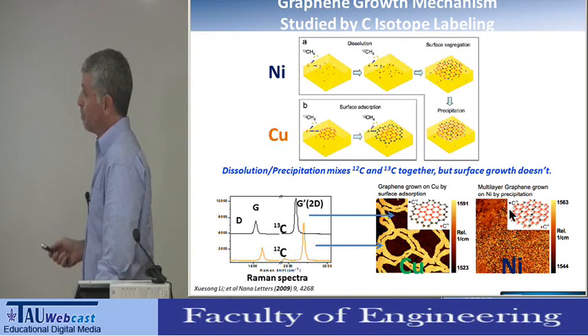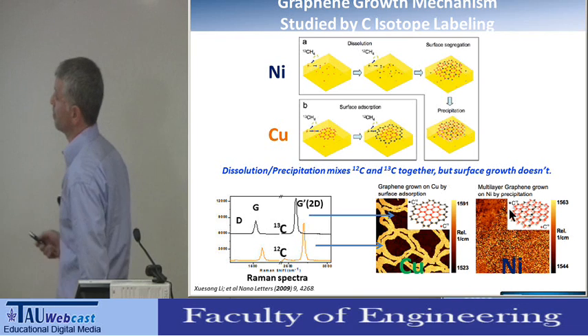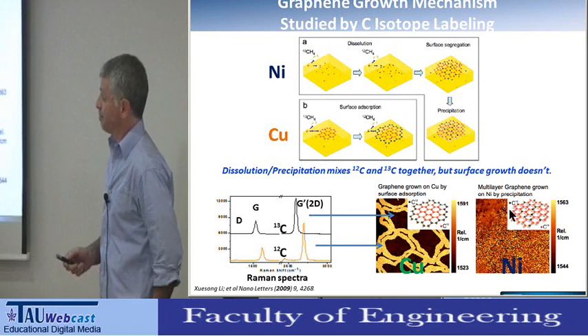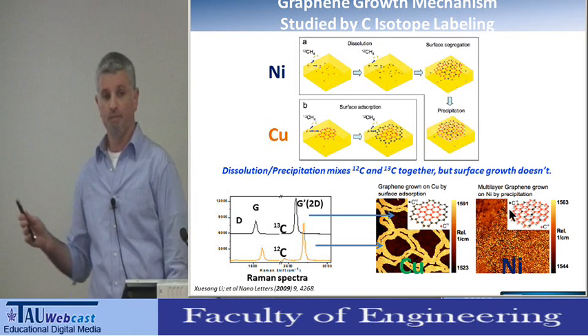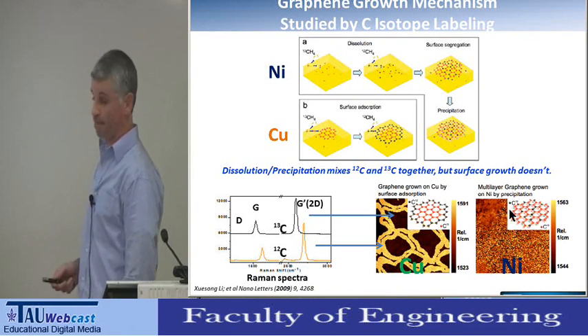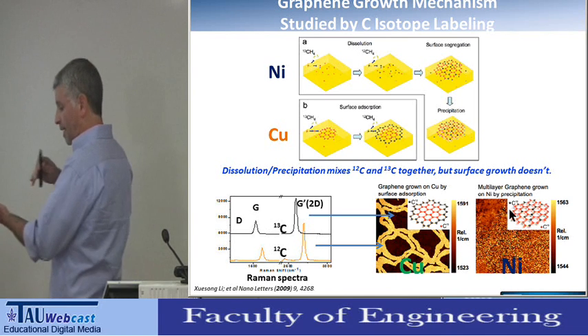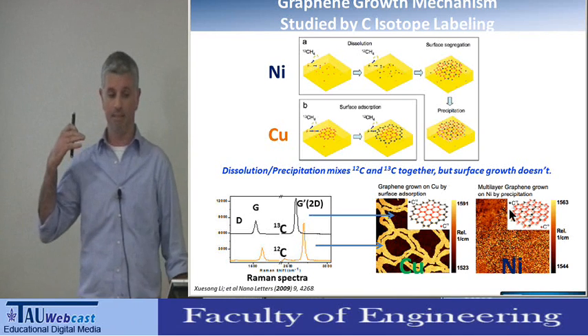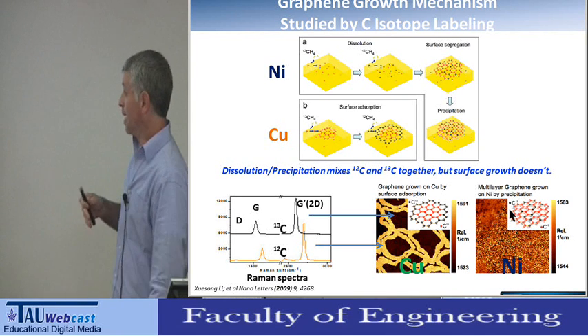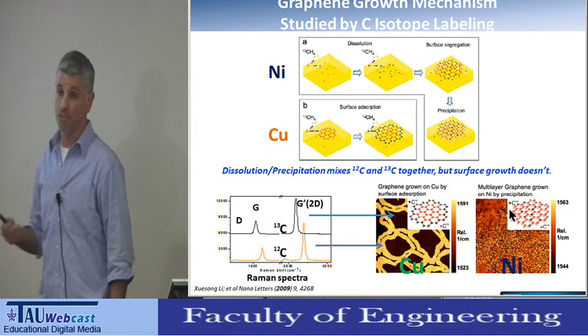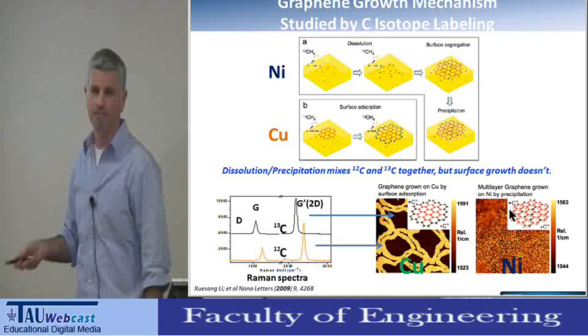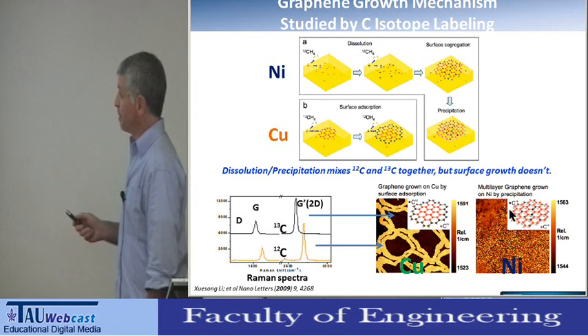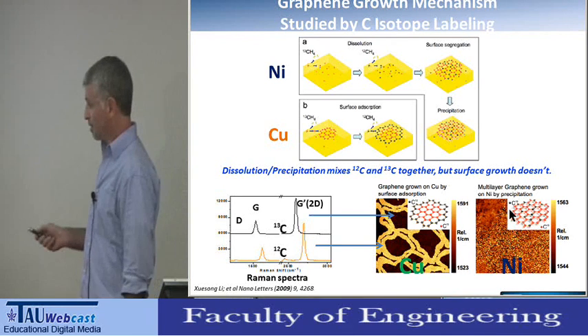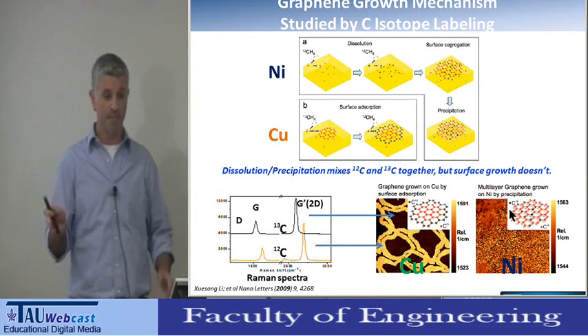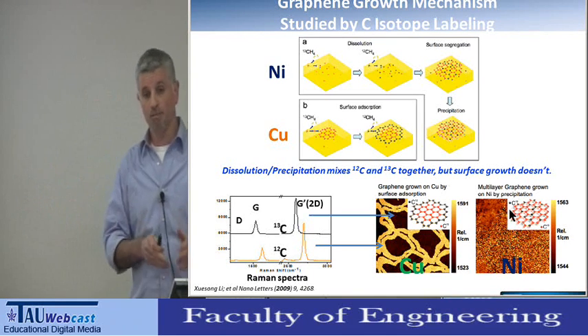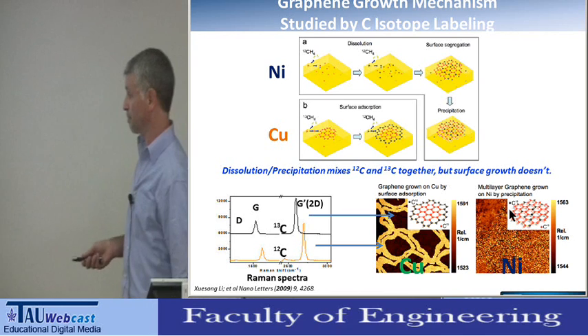Here you can see a comparison of two of the most common metals to grow graphene. The first one nickel, the second one copper. In our group, we studied the growth mechanism of graphene by using so-called carbon isotope labeling. In this case, you expose the catalyst sequentially to a hydrocarbon that is enriched with C13 carbon, and to a hydrocarbon that has a natural composition of carbon isotopes, which is 99% C12. After doing so, you can characterize it by Raman spectroscopy, and you are able to identify the regions with C13 and C12 by vibrational spectroscopy.